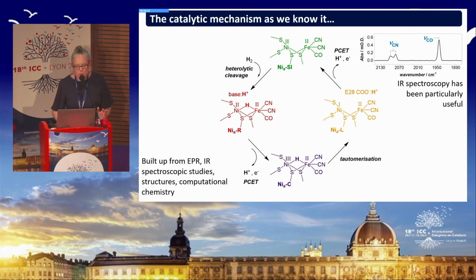So the mechanism for nickel-iron hydrogenases, as we know it, starts from this nickel-2, iron-2 intermediate with, well, I'll come back to this, but likely a vacant coordination site here between the metals. And hydrogen is cleaved heterolytically, unlike on a platinum surface, to give a metal-bound hydride here, the bridging hydride, and a proton on a nearby base. And that is still under contention, the site of that proton.